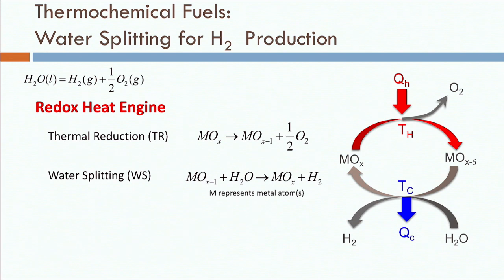So how do you do water splitting thermochemically? The most common approach is what is called a two-step reaction. It's essentially a redox heat engine. You take an oxide, you heat it, the oxygen comes out, now you've got vacancies in there, you expose it to water, and you reduce water to produce hydrogen, and then you turn this around. You've got heat addition at high temperature, heat rejection at low temperature. This is a heat engine. The work is a redox work.